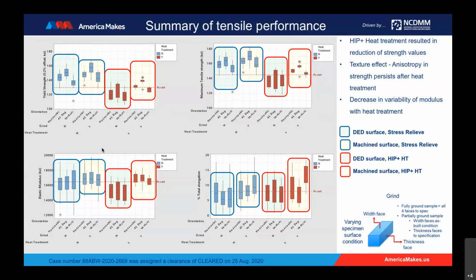With regards to the surface finish, there appears to be a trend within a given orientation. The fully ground specimens tend to have a higher value than the as-built surface specimens. Now this is convoluted by the challenge in measuring the cross-section with the as-built surface finish, and also the influence of the surface finish itself on the performance. But those are the biggest takeaways here. So then now if you were to look into the effects of the process parameters itself, show me, if you could go to the next slide, please.